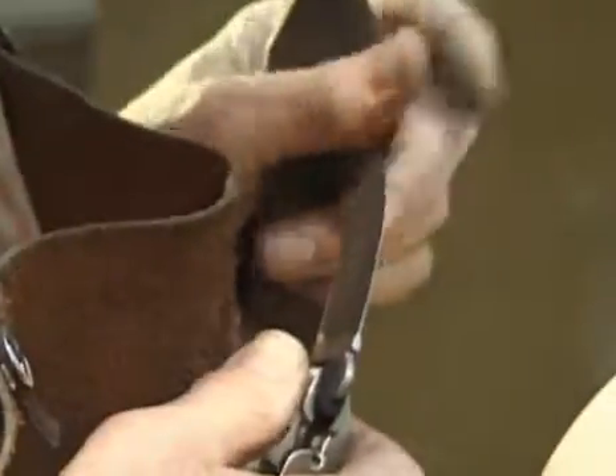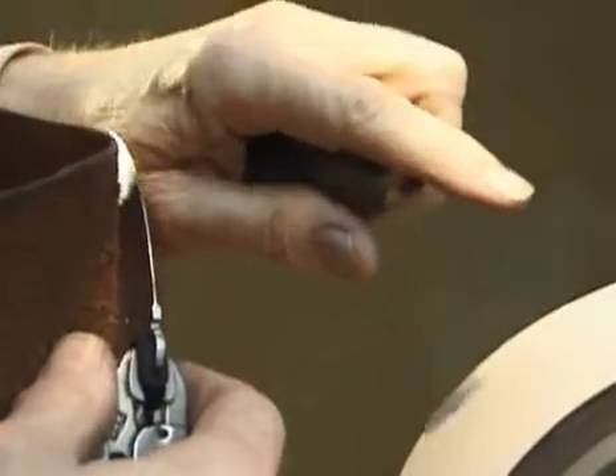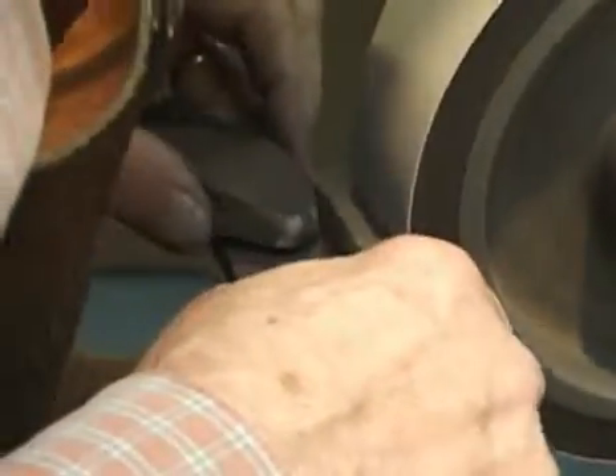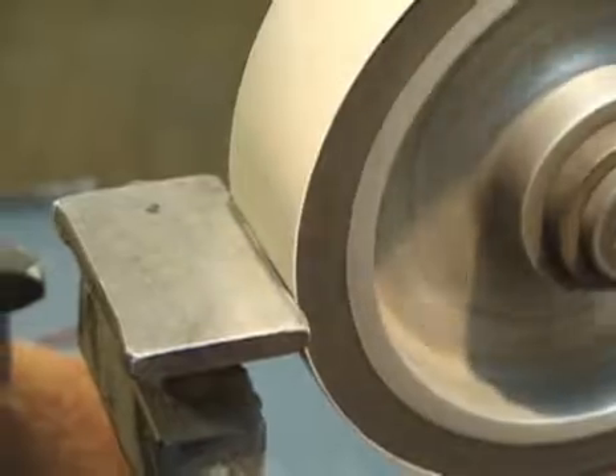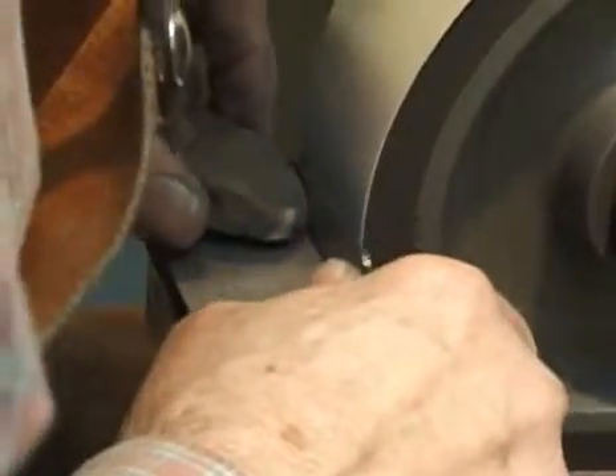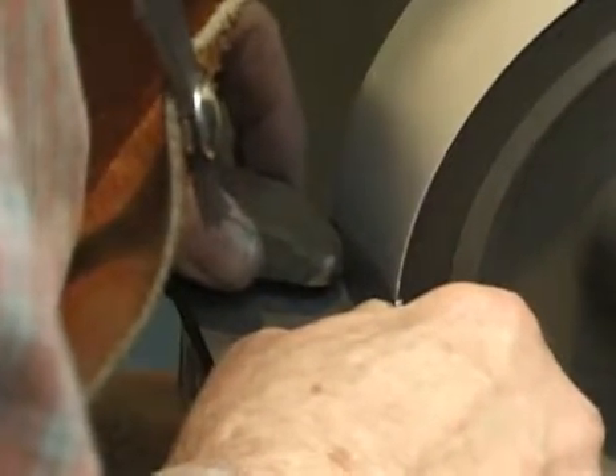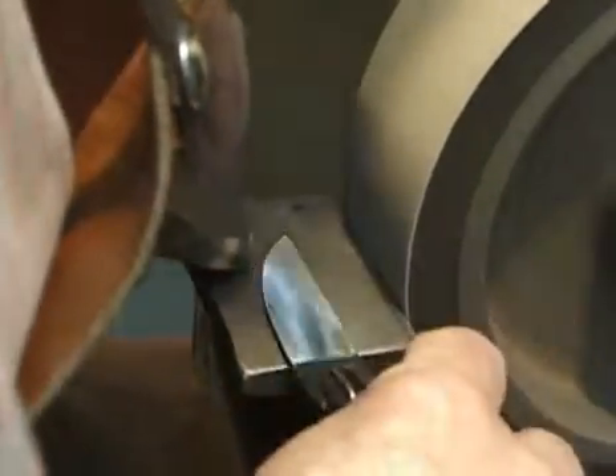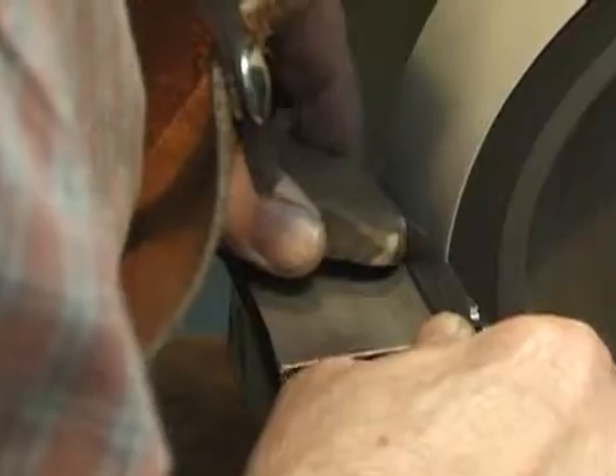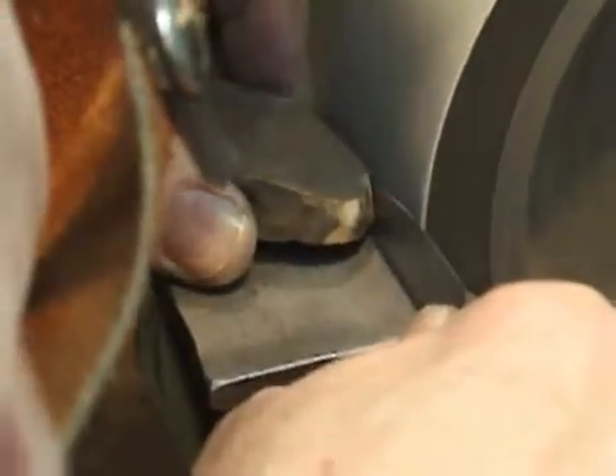Okay, we just finished making a couple of passes on these blades with the 320 grit belt. Now we're going back to the Norton X22, which is about a 400 grit. We're going to hit a couple of passes with this, and then we'll be through, except for the hand finish. I'm turning my grinder down real slow. You can almost count the revolutions as it goes around, because I want to have a lot of control. You know, I'm doing more polishing now than I am removing metal. I'm trying to remove those 320 grit scratches that are in there, and I'm just basically trying to grind off the tops of those scratches, bring them all down. Bring them all down even on the blade.